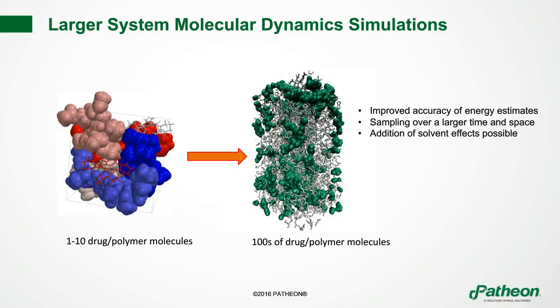So, as Tom was saying, initially we will run simulations of anywhere from 1 to 10 drug molecules and a few polymers. But as you see in the middle, with our high-performance computing platform, we can run hundreds of drug molecules and polymer molecules at the same time. Typically, you have between 1 and 10 drug molecules and some polymers that will run in the simulation locally. But when we want to get more accurate energy estimates, we want to sample over a large time and space and even deal with solvent effects or other excipients that might be included in the dispersion, we'll need to go to a high-performance computing platform where we can model hundreds of drug molecules and polymer molecules at the same time. So these are now simulations of tens of thousands or even hundreds of thousands of atoms.